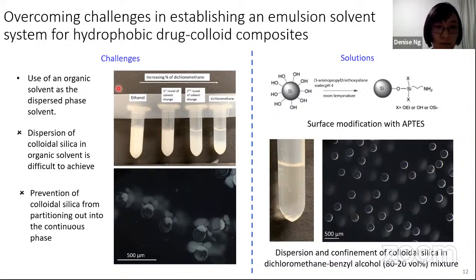So here we have to use an organic solvent as our dispersed phase solvent instead of using water as we did in the case of lamivudine. And with this, it is difficult to disperse colloidal silica in an organic solvent. So here I have an image of trying to disperse colloidal silica in dichloromethane, one of the commonly used organic solvents in oil and water emulsions. And secondly, the other issue is that we need to prevent the colloidal silica from partitioning out into the continuous phase, as you can see over here. Otherwise, the colloidal silica will not be able to exert its effect during the crystallization process.